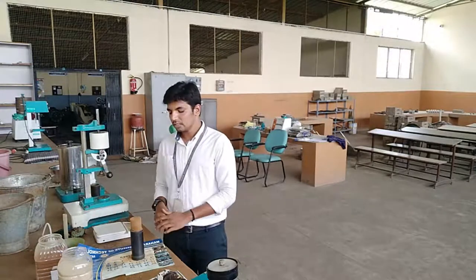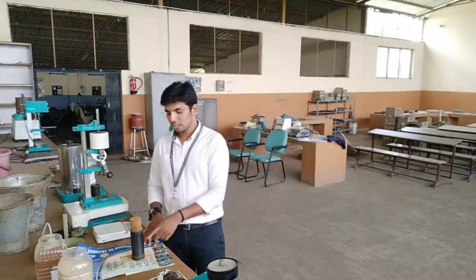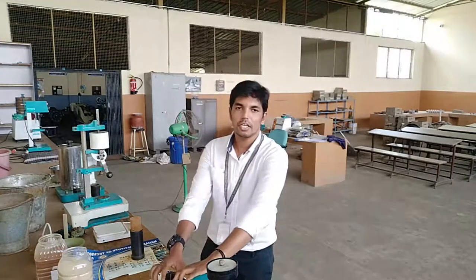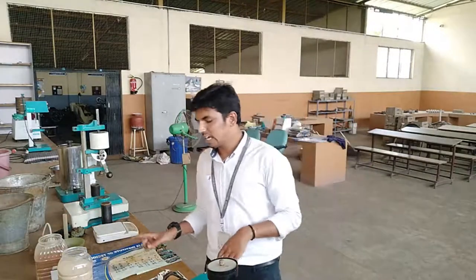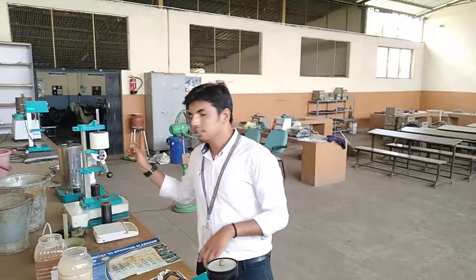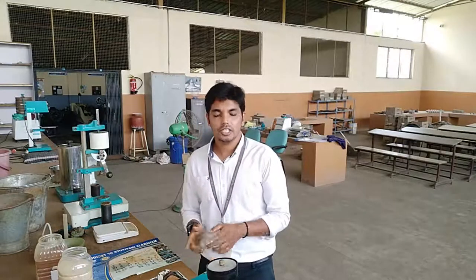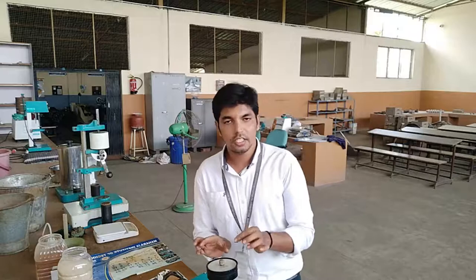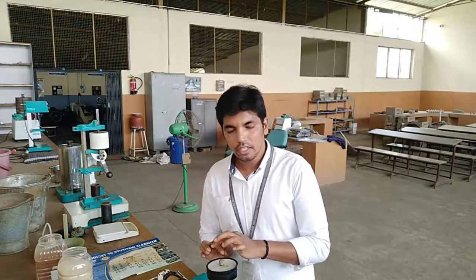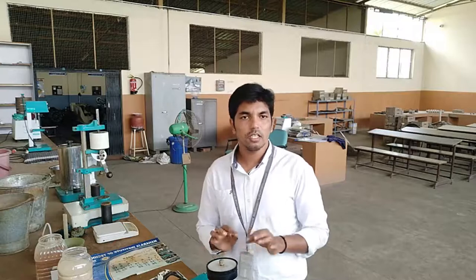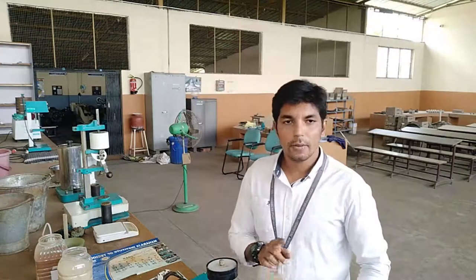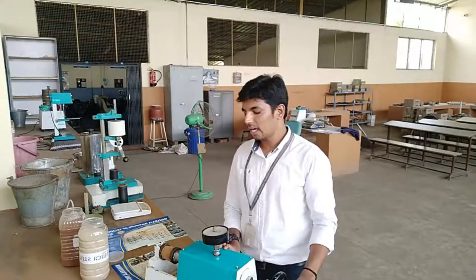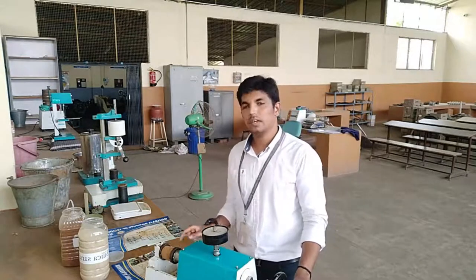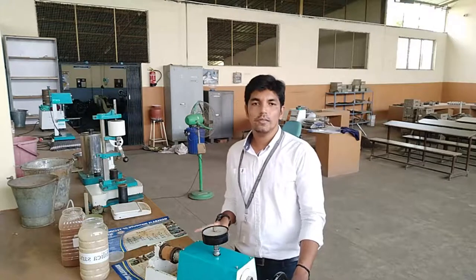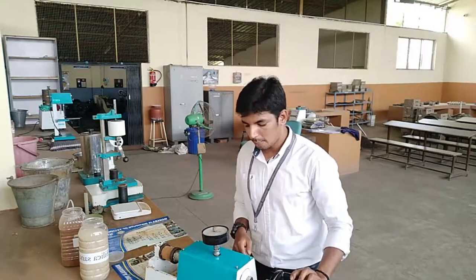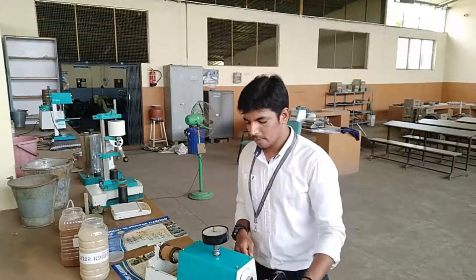Now I am carefully transferring the specimen from this position to in between the pressure pads of the shear testing machine. Now I have transferred the specimen from the sand rammer to the pressure pads of the shear testing machine, and now initially setting the dial gauge reading at the shear scale to 36. Now I am carefully applying the compressive force with the help of the anvil. Due to the application of compressive force, first the specimen will undergo compression, and later it will undergo shear failure.